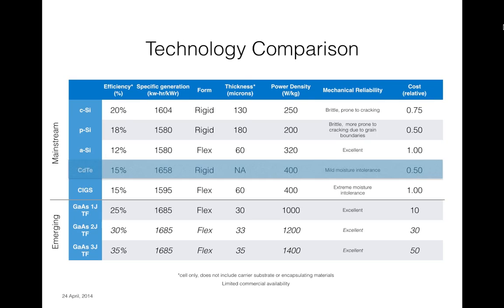Now, CIGS is a candidate for these UAVs, along with the amorphous silicon, for applications that could support that power density and ultimately that energy density. And I tried to give you a figure of merit here with regard to energy density, and I know I haven't spoken at all about that second column labeled specific generation. I'm going to circle back to that in just a minute. But I'll tell you what that factor is. That's the amount of energy that you would expect to collect on a per watt rated basis. So earlier I said that all these materials, their efficiency is measured at standard test condition, which is 25 degrees C, 1,000 watts per meter squared irradiance.